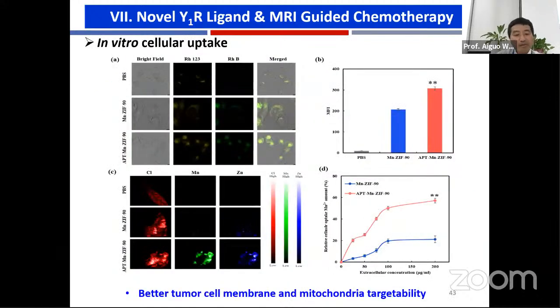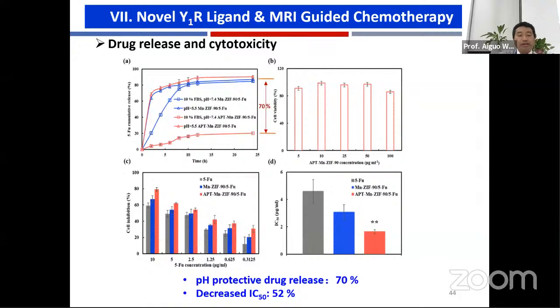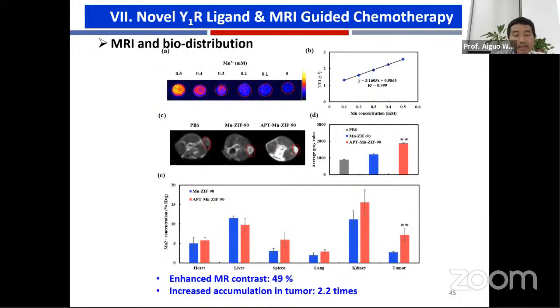And we used the Shanghai synchrotron facility. We can obtain the data showing the tumor cell membrane and mitochondrial targetability there with very good signal enhancement. And also, it is a kind of pH protective drug release of about 70% and also decreased the IC50 by about 52%. And it enhanced the MRI contrast by about 49%.